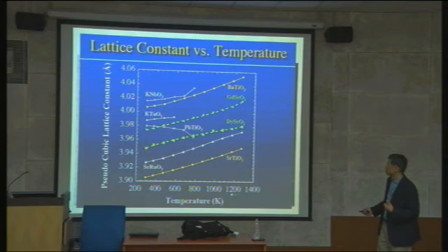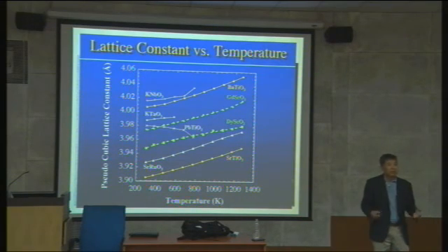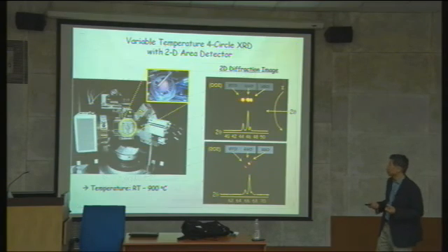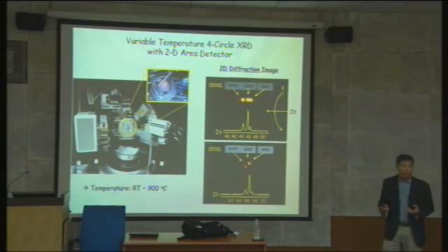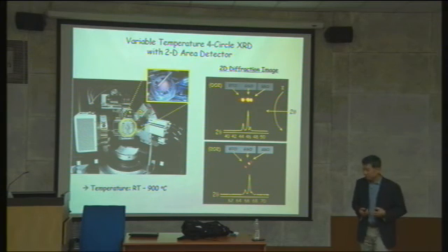So as a function of temperature, the strontium titanate, this gadolinium scandate, dysprosium scandate, lead titanate, the slope looks very similar. Okay? So that means the slope is very similar, and I think I can use this room temperature lattice parameter data as good enough to first approximation. Okay? That's one. And then for this kind of measurement, I think this one needs more learning of X-ray diffraction, but I'm going to briefly talk about X-ray diffraction.